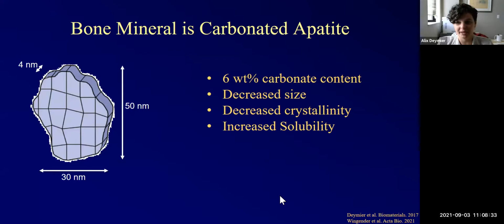And that 6 weight % carbonate means that we go from having a centimeter-sized hexagonal crystal to suddenly having nanometer-sized crystals that are about 50 by 30 by 4 nanometers that have this kind of platelet shape. On top of changing from big crystals to small crystals, we decrease the crystallinity and we increase the solubility. So biologically, by adding carbonate, we actually have smaller crystals that are less crystalline and more easily dissolved. Well, that seems perfectly handy to serve as a carbonate manufacturer. So these crystals seem to be tuned biologically to be carbonate releasers.